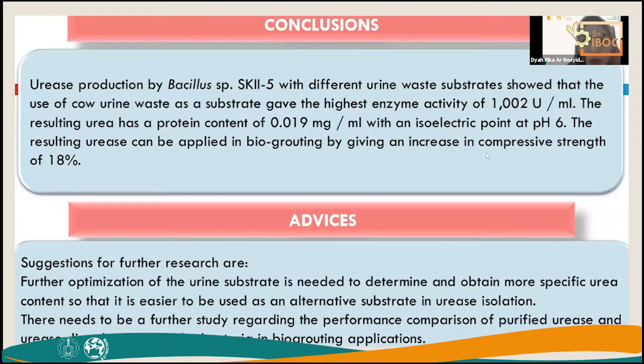So this is the conclusion of the study: urease production by Bacillus sp. SKII-5 with different urine waste substrates showed that the use of ruminant urine waste as a substrate gave the highest enzyme activity of 1,002 units per milliliter, and the resulting urease has a protein content of 0.019 milligram per milliliter with an isoelectric point at pH 6. The resulting urease can be applied in biogrouting by giving an increase in compressive strength of 18%.